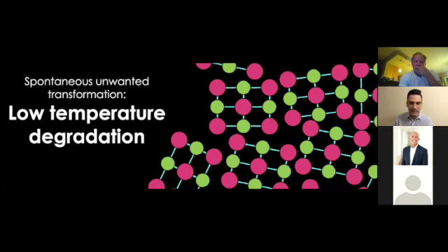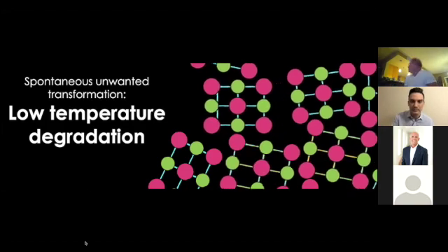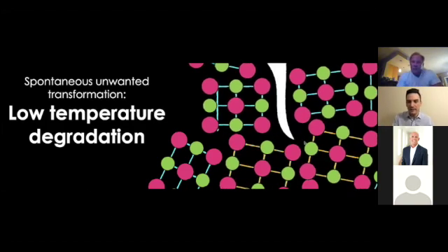And that's not so cool, because if they spontaneously transform and get bigger, then they're kind of pushing up against each other. And, you know, if you got something confined to a space and it all gets bigger, it's going to start cracking. And that's what was known as low temperature degradation, when they just kind of spontaneously get bigger and then they cause a crack.